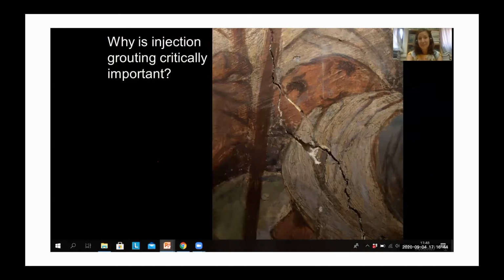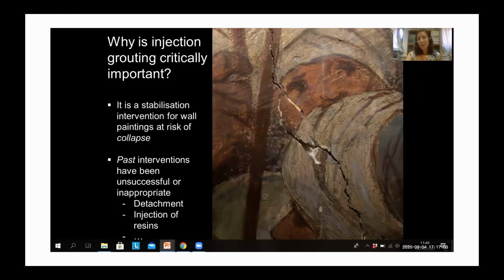And why is injection grouting quite important in some cases? It's a stabilization intervention for paintings at risk of collapse, as we have seen in the other picture, potentially. And because we know, sadly, that past interventions have been unsuccessful or inappropriate. For example, detachment might have been successful, meaning that the conservators were actually able to detach the wall painting. But of course, the nature of wall painting is to be bound to the building itself, so it is a change of nature of it, let's say. Or in the past, different materials were injected, such as resin, which have a different physical mechanical behavior, and so can put the wall painting itself in danger.